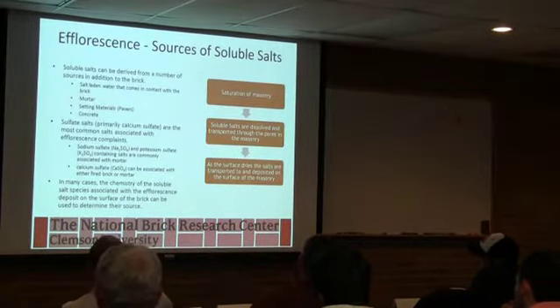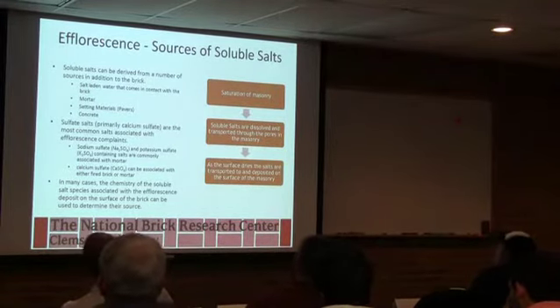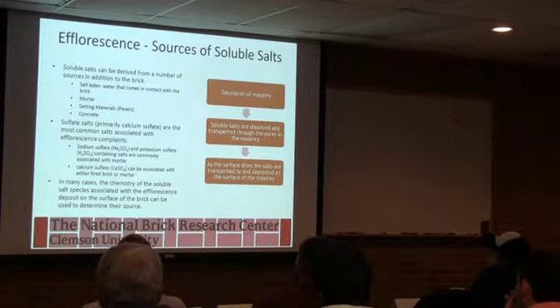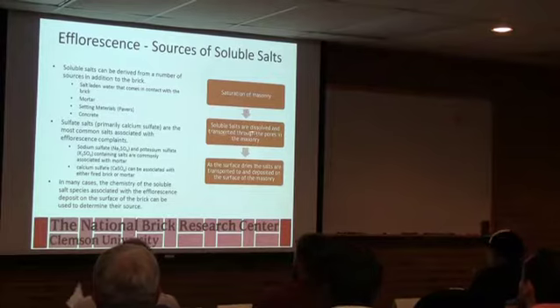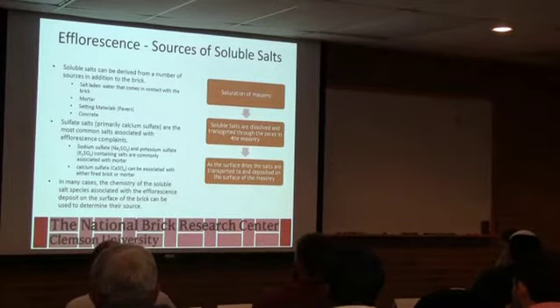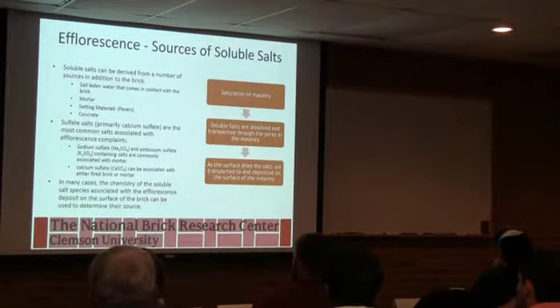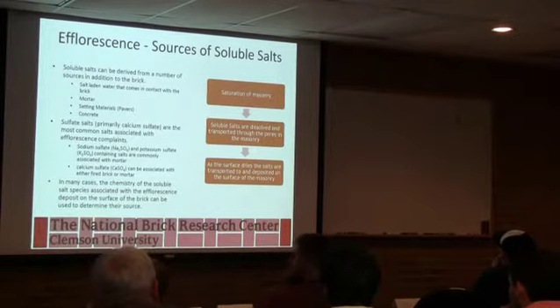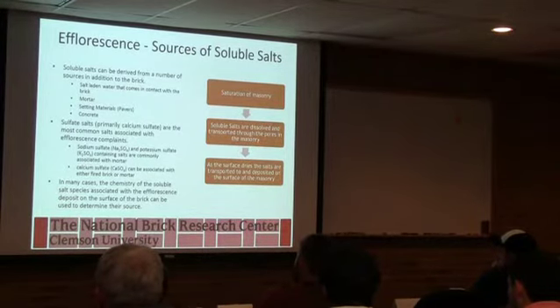All right. So efflorescence has a cycle. The salespeople and the people that deal with complaints talk about this a lot. We've already talked about it a little bit, but the brick get wet, there's soluble salts present, and in a lot of these cases, we're looking at mortar or concrete or other cementitious materials that the brick's in contact with. They have an unbelievable amount of soluble salts that can end up in the brick and on the surface. And with that tool I just showed you, we can figure out where they came from.